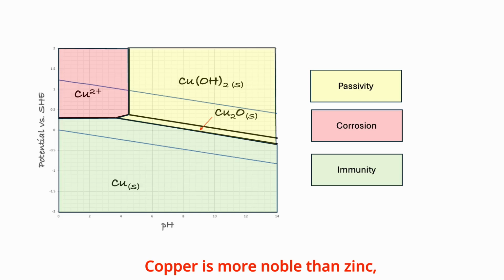Copper is more noble than zinc, and its region of immunity extends towards significantly higher potential values. At low pH and relatively high potential, copper tends to oxidize, forming copper ions, with oxygen reduction as the only feasible cathodic reaction, as the line for copper oxidation lies beneath that for oxygen reduction. Conversely, hydrogen evolution is not thermodynamically viable during copper corrosion, as its line always sits below the copper oxidation line. In high pH conditions, copper has passive behavior, indicated by the formation of stable oxide or hydroxide films on its surface.